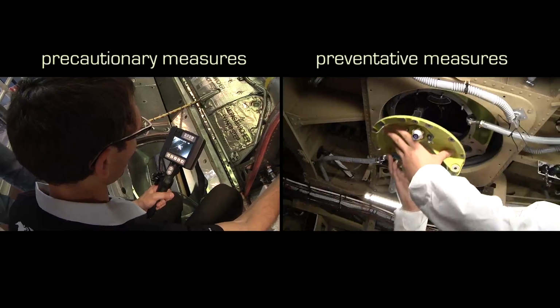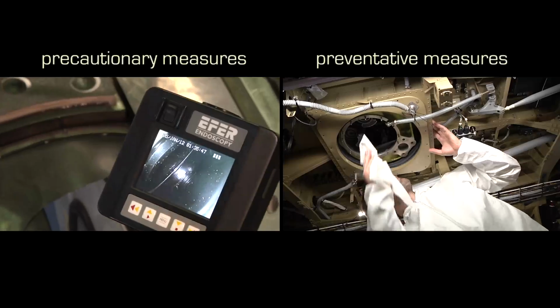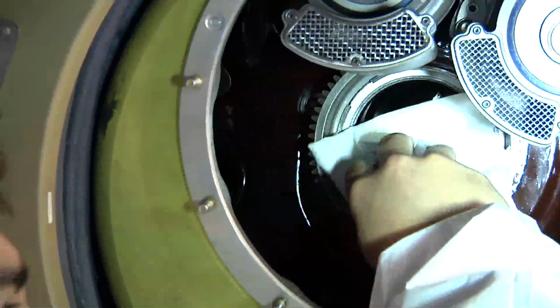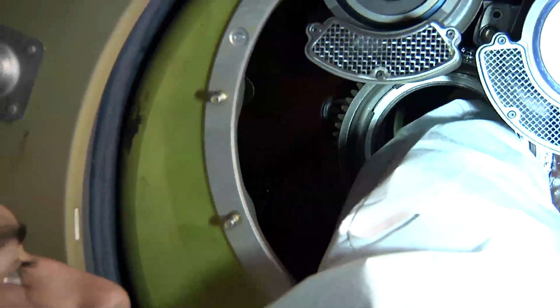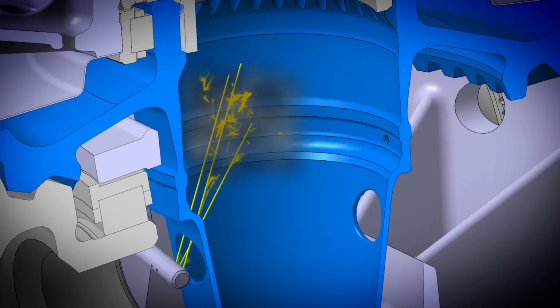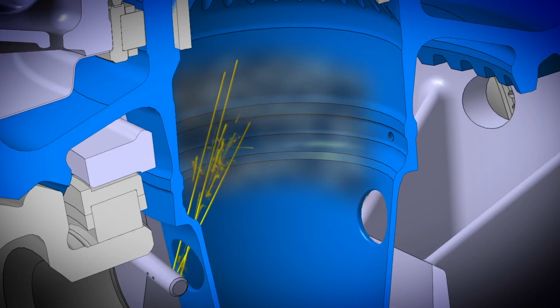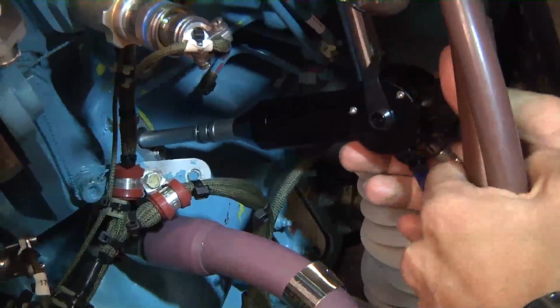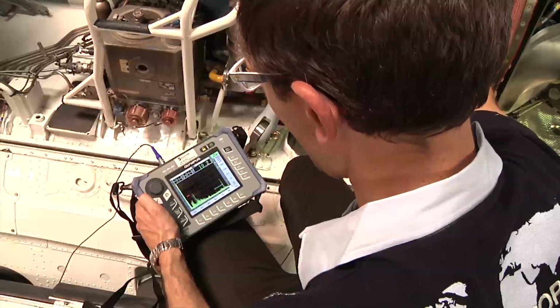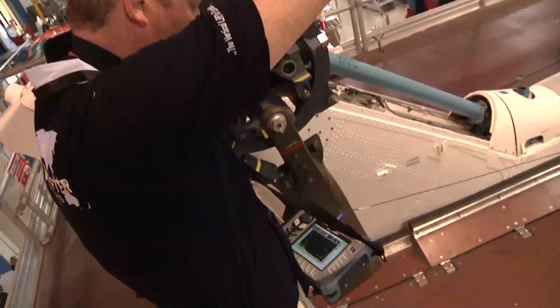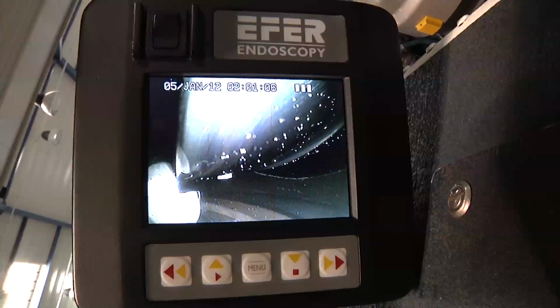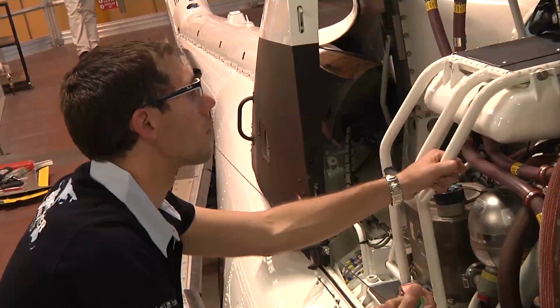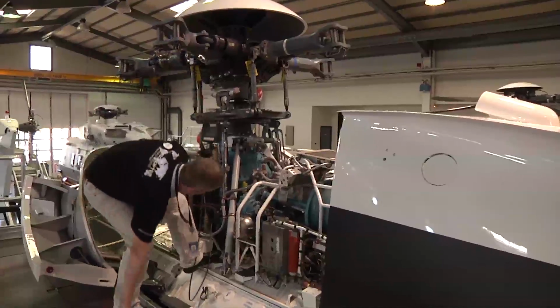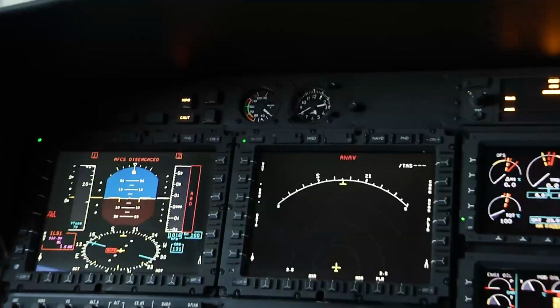The safety measures proposed by Eurocopter are divided into two categories. Preventative measures: redesigned welding hole plug as well as manual and automatic cleaning should prevent any crack initiating. Precautionary measures: ultrasonic non-destructive inspection and in-flight permanent monitoring of shaft condition. These additional measures provide a simplification of monitoring and detection means to ensure that if there are any cracks, they are detected early, well before they have had time to grow to the point at which they could threaten the integrity of the bevel gear vertical shaft.